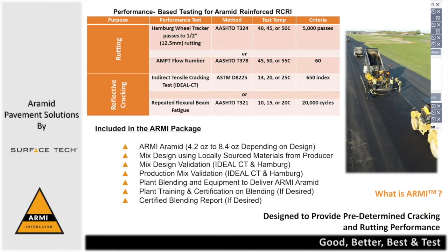From a reflective cracking standpoint, we're going to run IDEAL-CT, and it will be better than 650 in index anywhere in the country that this product is made. And as you can see from the bending beam fatigue test, a minimum of 20,000. Now, we will share with you that what we've developed in Kentucky is actually quite a bit better than that, about 30% better in both categories.